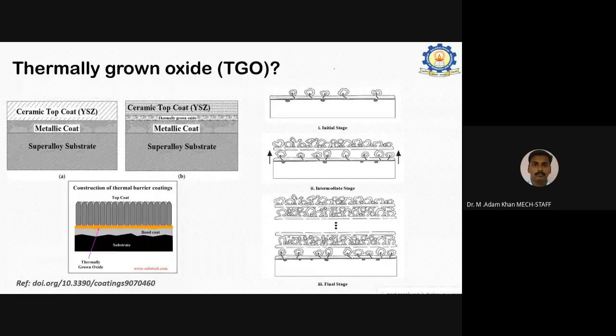So this is the oxide scale. Sorry, this is the coating, top coat or ceramic coating. When the coating lets oxygen through these micropores towards the substrate, it starts to make localized corrosion. This is called localized corrosion at the pores or the voids. It will produce a uniform corrosion film, an oxide film, that is called TGO. When the oxide grows, it will shift this coating layer from the substrate to the top. It raises just like a mushroom, and it takes the coating out of the bond coat.